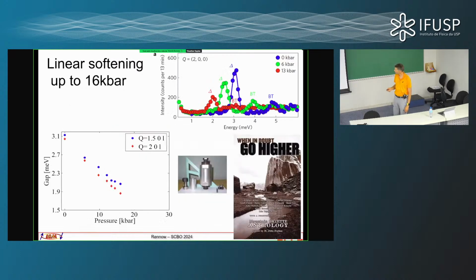So we started doing that. We applied pressure, and what we saw was that as we increased pressure, the energy of this gap to the triplet excitation goes down. That's great news, because generally when you have a phase transition between one state and another state, if it's a second order phase transition, you actually expect the characteristic excitation to soften, to go to zero, and then you get the new phase when that excitation reaches zero. So this is good news.